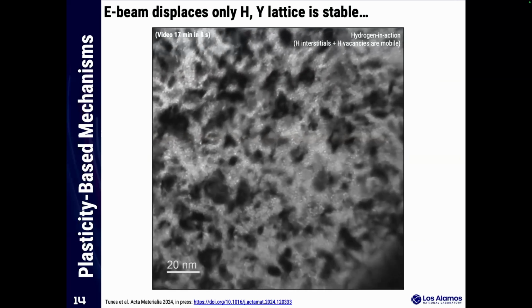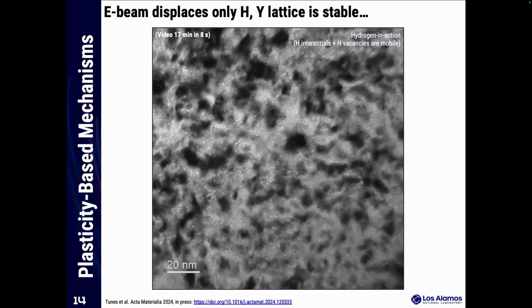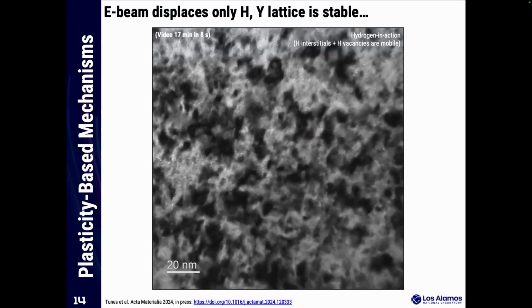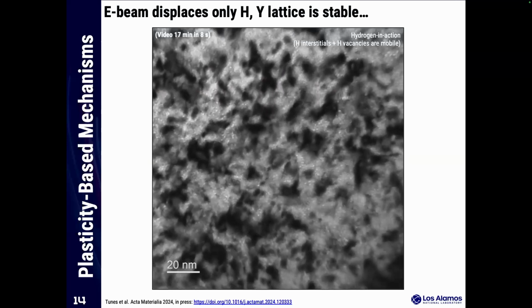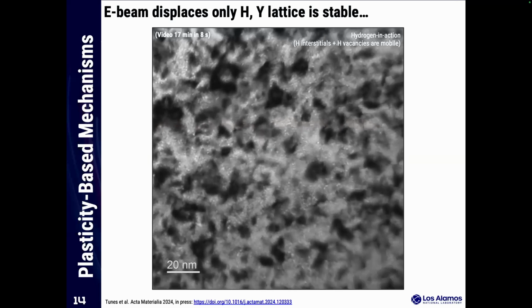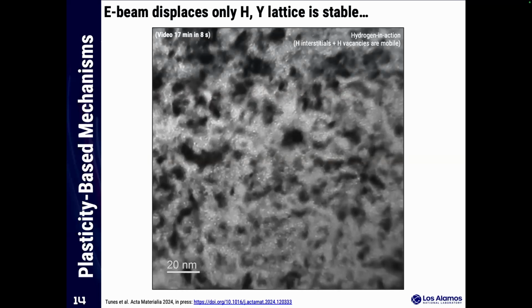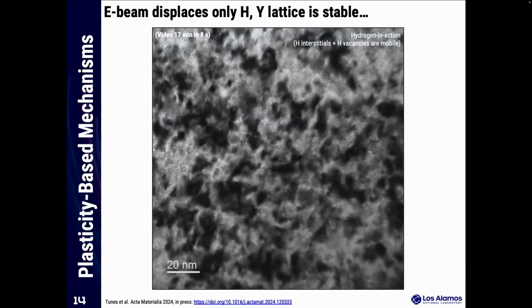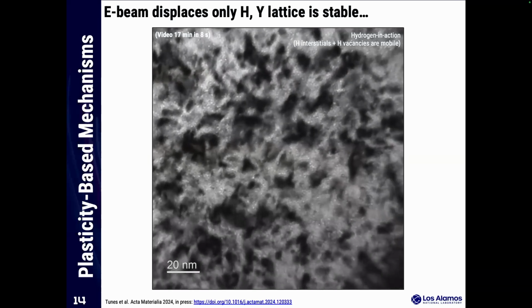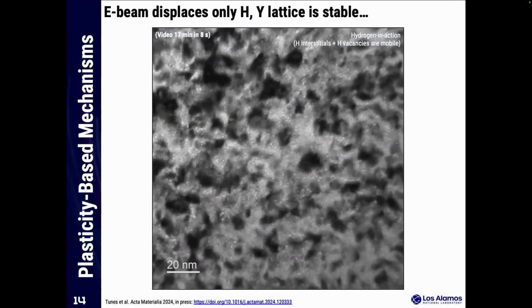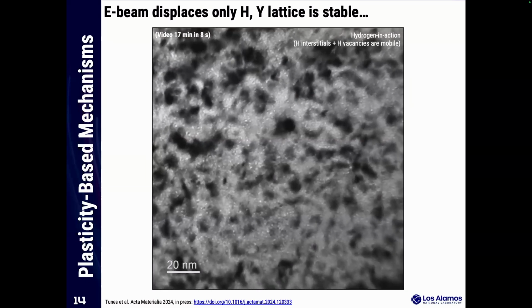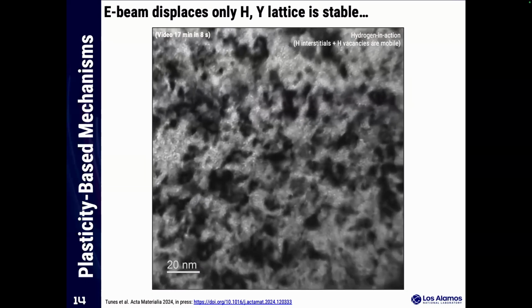Actually, this is a very interesting experiment. This is pure yttrium hydride. When you focus the electron beam in the TEM, you can displace the hydrogen, but not the yttrium. So you have a very interesting platform to study hydrogen embrittlement. If you see at the beginning, we have some dislocations, and when the hydrogen is mobile, the dislocations annihilate, and you form a lot of voids.